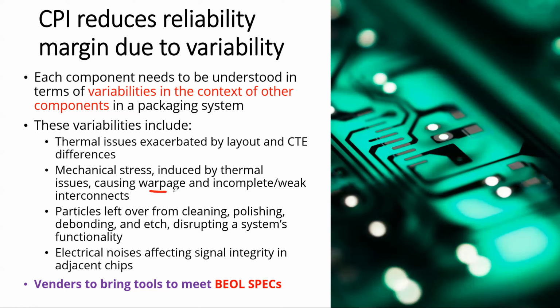The mechanical, the warpage is very easy to see. When you make it, you find out, oh, it warped. You're over your spec. Your spec may be 5 to 6 mil, and then you have warpage that's over 10 mil, then you're in trouble, right? So all these are easy to see. And then particles are harder to see, but because of your packaging scaling, we are going to denser and denser HBI, the hybrid bonding interconnect. The pitch is so small. So imagine if a particle sits on top of the bonding interface, then you ruin it, right? So the particle definitely plays a key role.